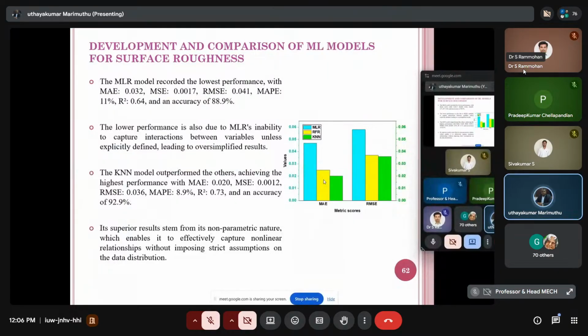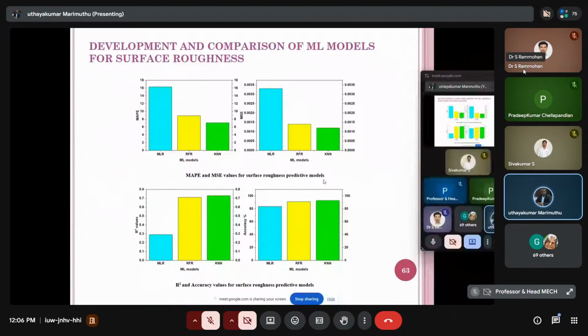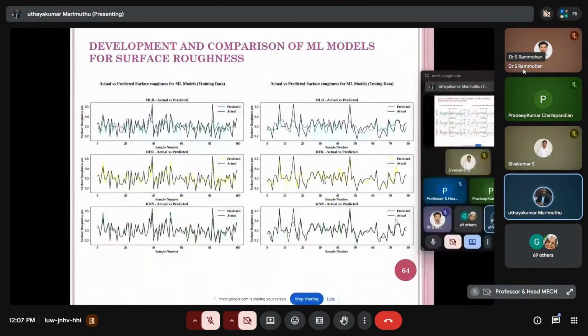The KNN model outperformed the others, achieving the highest performance with the other values ME, MSE, and R, and the reported accuracy is 92.9%. It is superior. Results stem from its non-parametric nature, which enables it to effectively capture non-linear relationships without imposing strict assumptions on the data distribution. This is the comparison of the sample MLR, RFR, and KNN, so you can understand how it should be compared at the end.